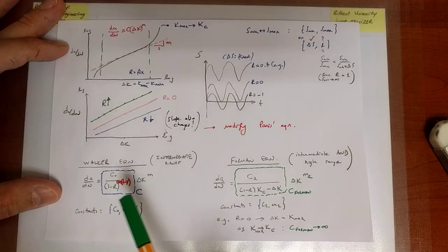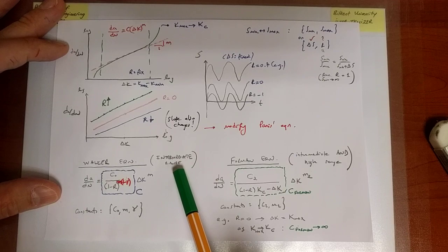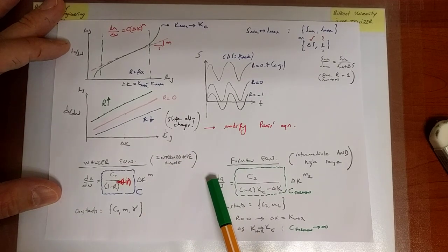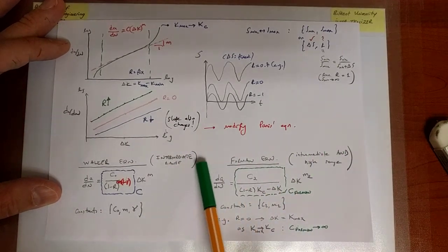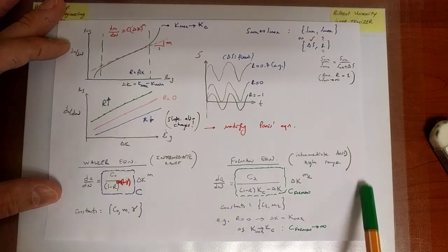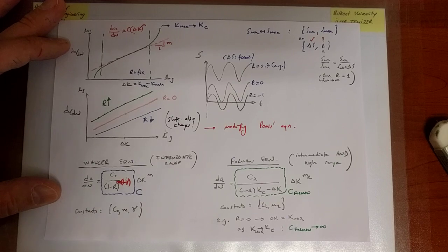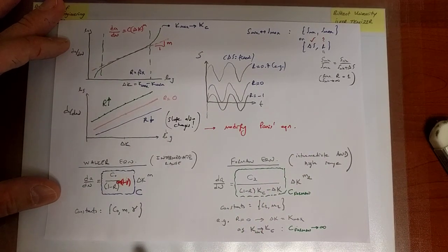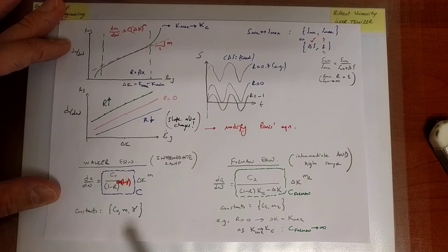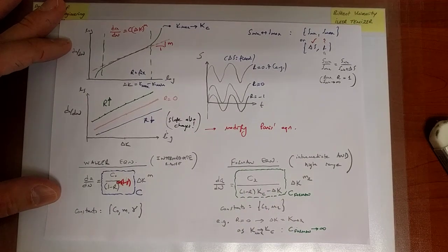And then we realized that, well, that only is valid up to the high range. So we've also incorporated the rapidly increasing crack size within the high range through the consideration of the physics, which is the fact that the stress intensity factor is approaching the fracture toughness, and that causes the rapidly increasing rate of the crack growth rate. Okay, and that's the Foreman equation.